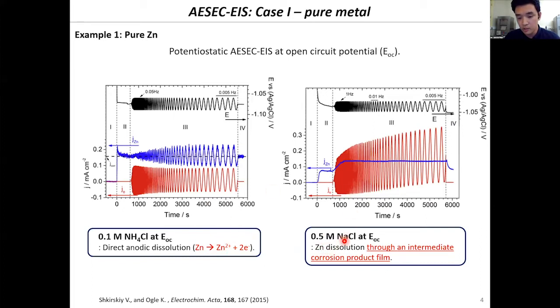Whereas when we change the solution to sodium chloride, we are no longer seeing this nice oscillation in the zinc dissolution rate, which is in blue. Whereas we of course still see the oscillation of the total current, which is in red.